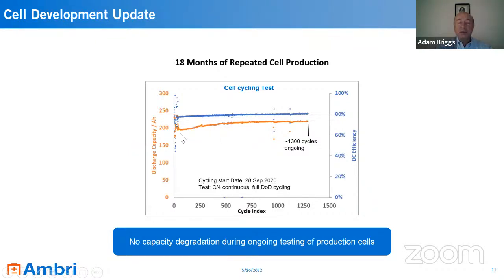You can see here some cycle data. One of the unusual things about these cells is that their capacity typically increases over the first 1,000 cycles, and then it flattens out for the remainder of its life. The same is true for efficiency, typically rises and then flattens out for the rest of its life. So we forecast no degradation in efficiency or capacity over those 20 years, although we do provide a guaranteed warranty of no more than 5% degradation over that period.